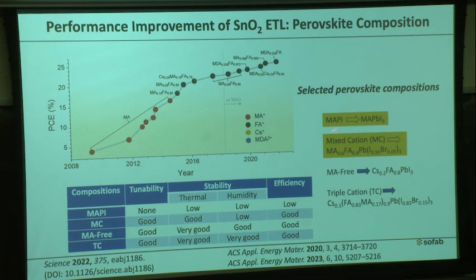In the same way, we selected 4 different types of perovskite based on their properties. First, people are using MAPbI3, so we use the same perovskite. After that, we went to mixed cation perovskite, which has higher tolerance towards temperature. Then another mixed cation type, and after that we made triple cation, which contains cesium. Cesium increases tolerance towards humidity, and formamidinium increases tolerance towards high temperature.